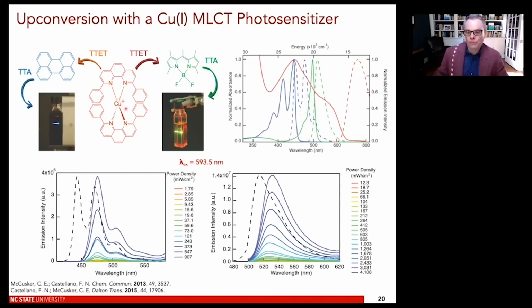So this is a red absorbing MLCT, or it's hard to call this really red absorbing because its absorption spectrum really extends out above 600 nanometers here. So you can excite in the red and generate green and blue fluorescence. And I don't think I have to go through all of the detailed experiments here again, but you recognize that as long as you follow that really original design criteria I mentioned earlier, you can get this to work with a lot of different donors and acceptors. And that's really the critical part of this.